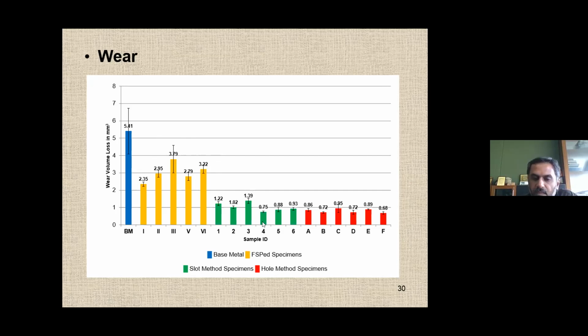And when you have hole method and slot method with the reinforcement like boron carbide, you see there is a further reduction in the wear. So that indicates a greater improvement in the wear resistance. The red are the best compared to all of them because it's a hole method. Hole gives you more uniform distribution of the reinforcement into the matrix compared to the slot method. In the slot method, you are putting all the material in one go, while in the hole method, they are already distributed at different locations. So the distribution into the matrix is very good.